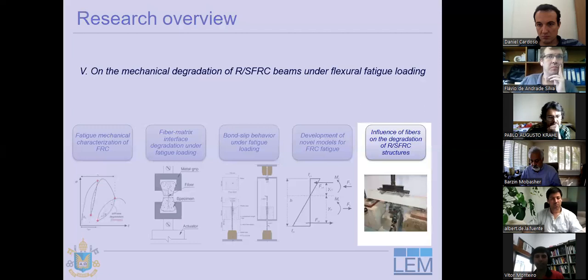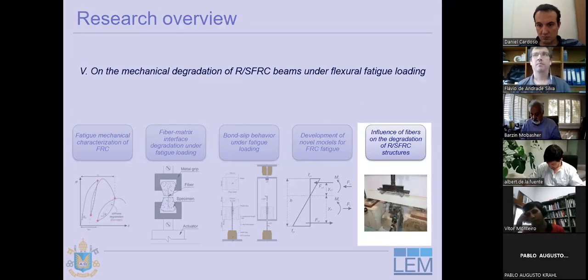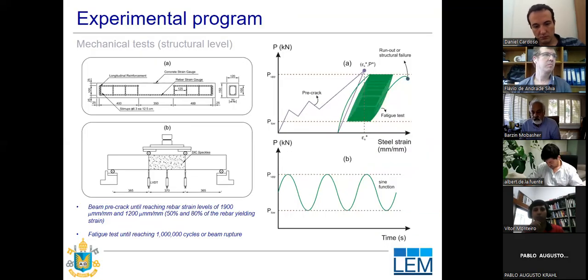And finally, the last section, I'm going to bring some results for the structural level and verify how the structure, a reinforced concrete structure with the use of fibers, degrades and mitigates along the fatigue loading. So the experimental campaign was based on a reinforced concrete beam, which was designed to present its rupture in flexure. We attached many concrete strain gauges along the face on the top, also to verify how the compression strains evolve along the fatigue test, and also gauges on the rebars to verify how the rebar strains are evolving under the cyclic loads. We also put some LVDTs to verify deflection along the test.